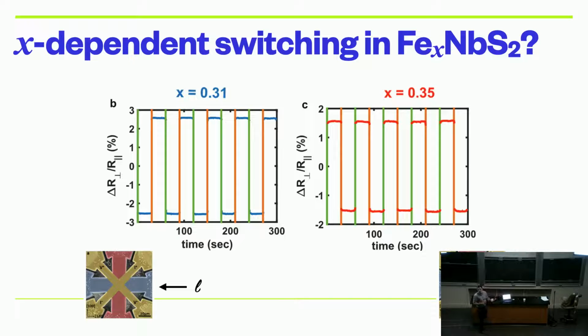Okay. Can you remind us what's the pure system's electronic property in iron niobium sulfide? It's a charge density wave, but I don't think it's... You sure the iron intercalation is not going to be in the lattice? Yeah, we did pretty extensive TEM, and the iron goes between the layers. The irons don't form clusters inside, they just sit as separate individual atoms. Not for this compound, they don't form clusters, but it's true when you get close to 1/4, you start to get clusters of 1/3 and clusters of other percentages.